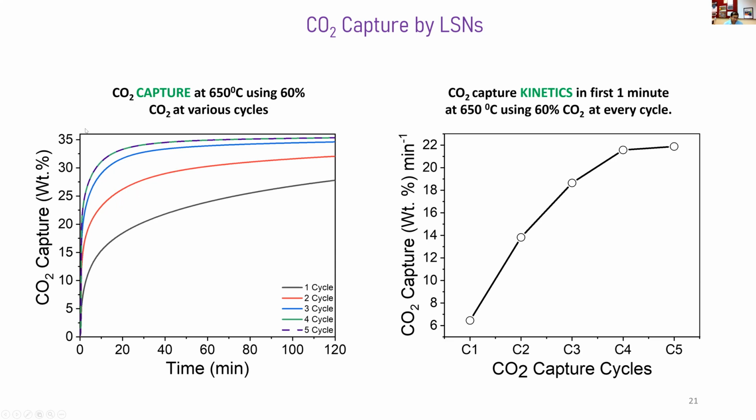And not only the CO2 capture capacity, which reaches around 32, 33 wt%, but also the CO2 capture kinetics change. You see, first cycle, it was 6 wt% per minute, then it will be 14, say 19, 21, and it remains there. So both the things are changing.